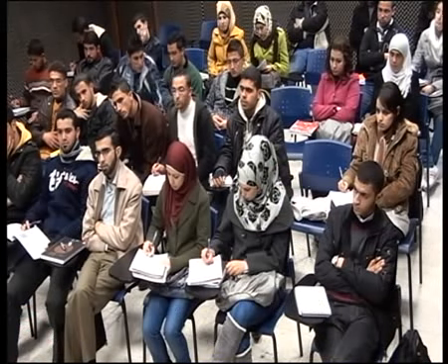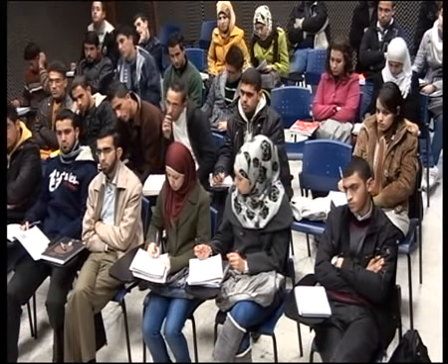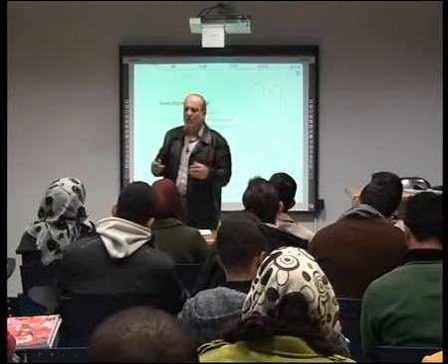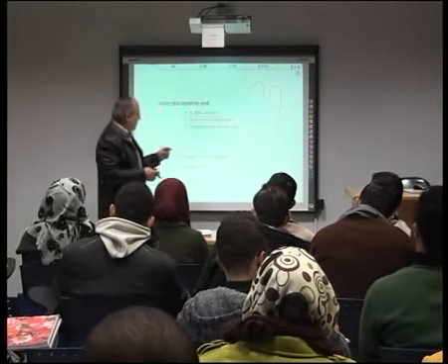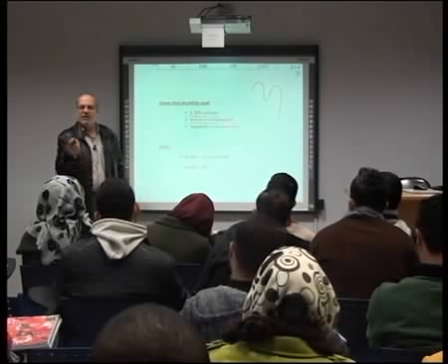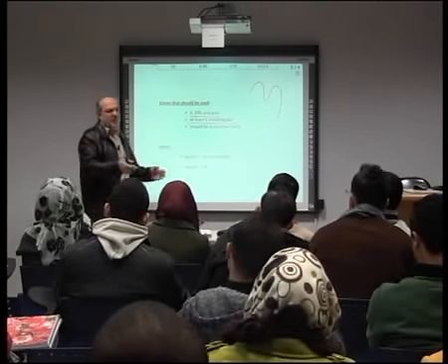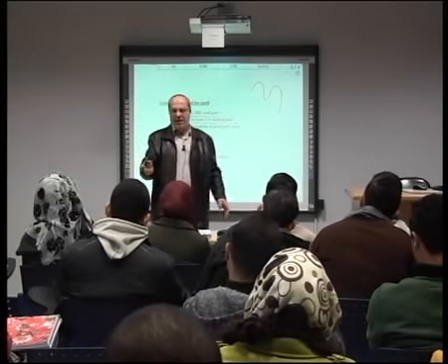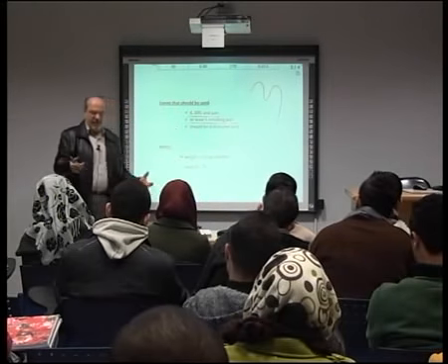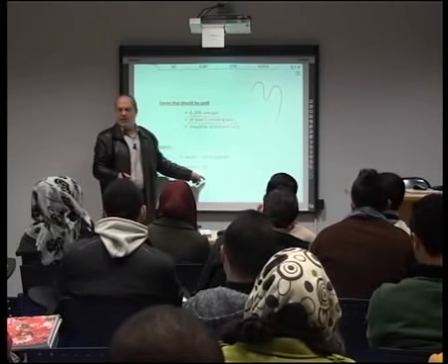Okay. Now, there is a human error. There are always human errors. There are always mistakes. There are always things that happen, especially when we deal with soils in number 200 or passing number 200, as if we are dealing with dust. So it may leak here or there. It may be lost here and there. So there may be some losses, but they should not exceed 3%.